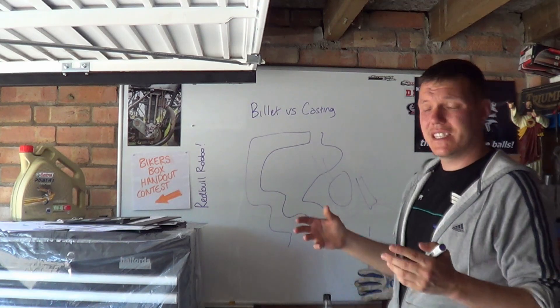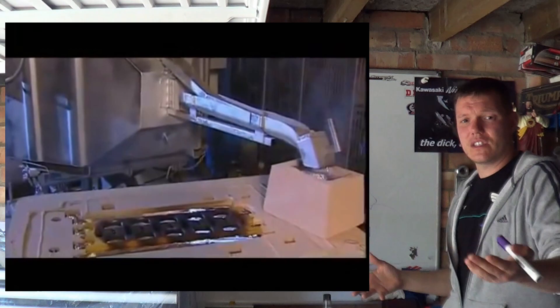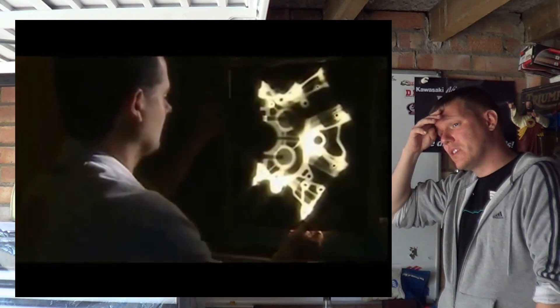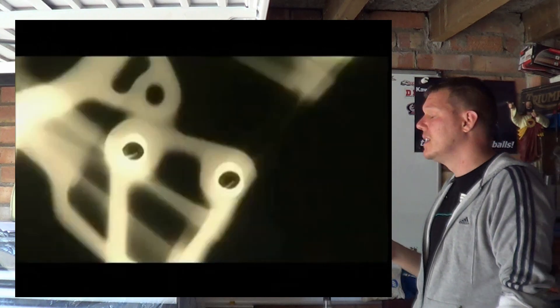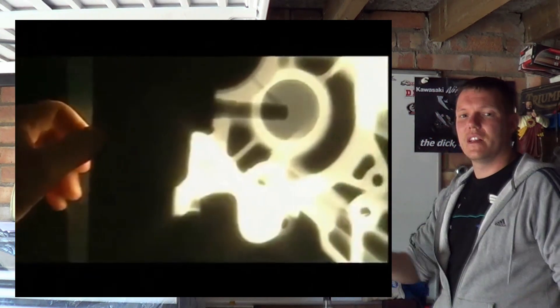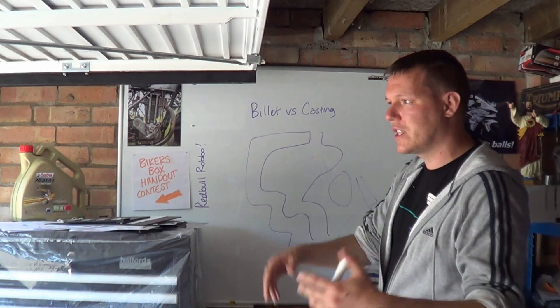This is why Ferrari still cast their engines. When they cast, like I said before, they x-ray their parts to make sure that they are top quality. There's no big voids in it or anything like that, gas pockets or anything stupid like that. And if they get a failure, they'll just basically chuck it in the recycling, melt it down again and just cast it again.